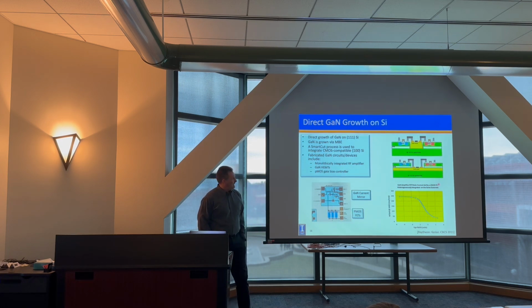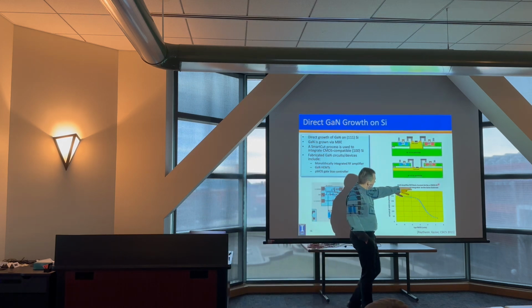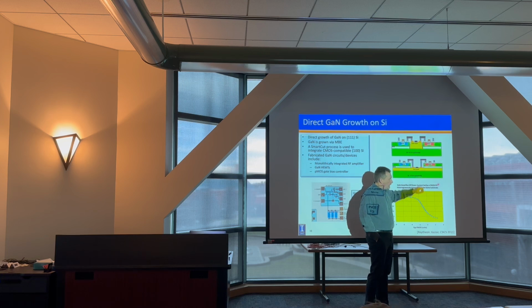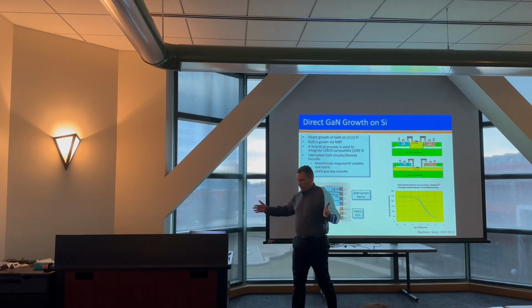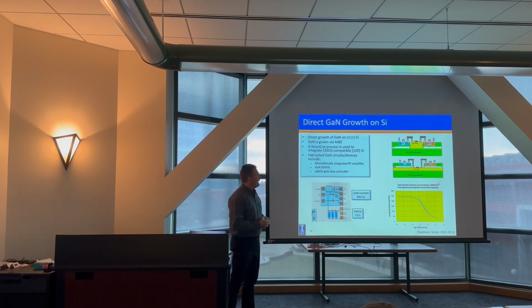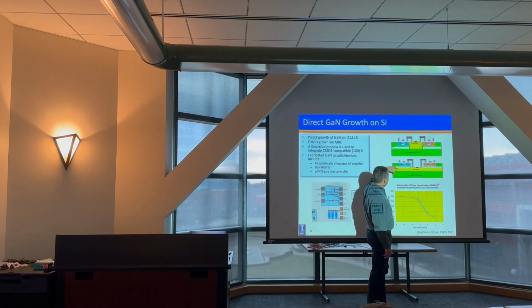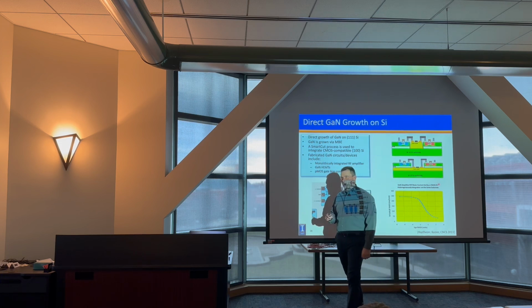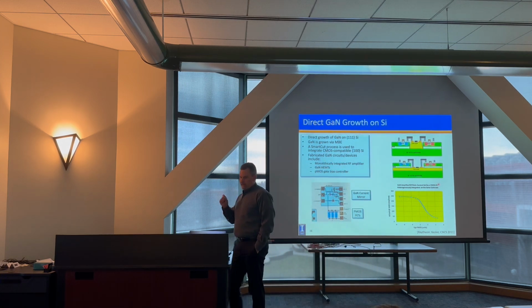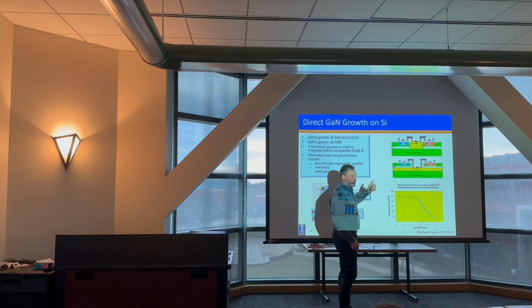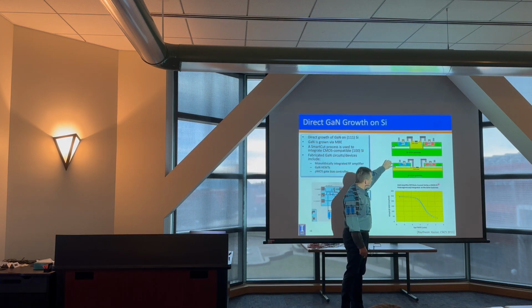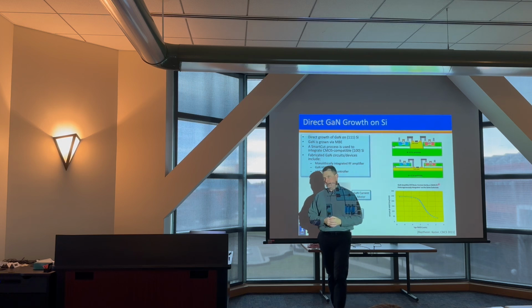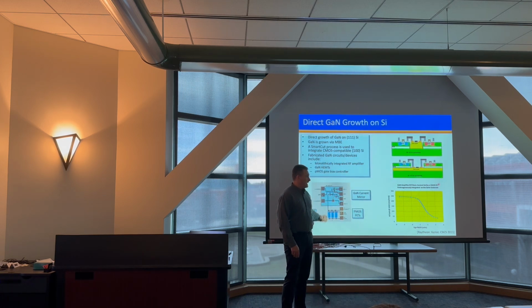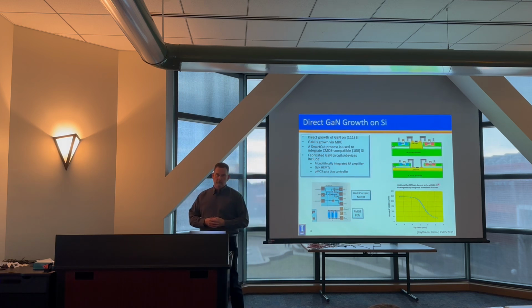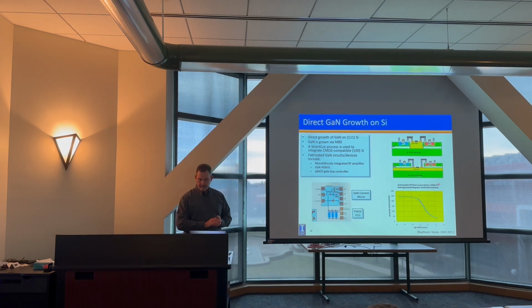Same is true of gallium nitride. This is sort of interesting work here. Here they basically grew gallium nitride on 111 silicon, which people can do at wafer scale. And then they put an oxide layer on here, wafer bonded a 100 silicon layer, and using ion slicing, similar to the technique that's used for making SOI, they produced a thin layer of that, and they made their CMOS circuitry on that. So they were able to integrate gallium nitride-based devices with basically silicon CMOS devices.